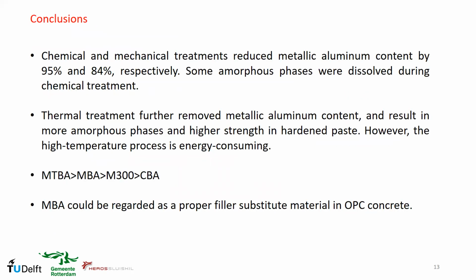So here we come to the conclusions. First, both the chemical and the mechanical treatments are effective in removing the metallic aluminum content. They reduced the metallic aluminum content by 95 and 84% respectively. And some amorphous phases were dissolved during the chemical treatment. Then the thermal treatment further removed the metallic aluminum content and also resulted in more amorphous phases and higher strength in the hardened paste. However, this high temperature process might be energy consuming.